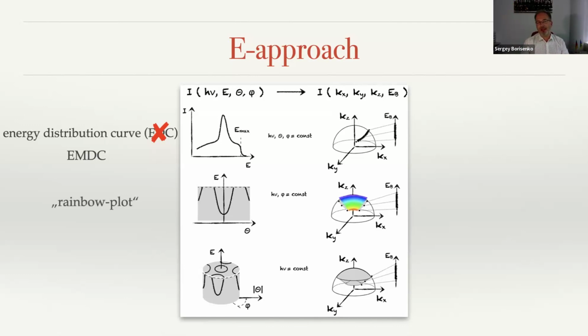Because of the angle multiplexing analyzers, not a single energy distribution curve is typically detected, but the whole range of these curves is detected. And this is why ARPES made revolutionary steps something like 20, 25 years back, because it was possible to record those with a very high angular resolution. This is a great achievement.